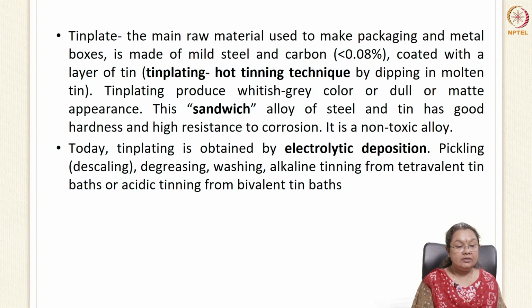Now tin plate steel is the main raw material which is used for developing cans and metal boxes. So it is made of mild steel and the carbon content is below 0.08%, and it is coated with a layer of tin, and this coating is called tinning or tin plating. This technique is the hot tinning technique, and it is generally done by dipping the sheet into molten tin, and this gives a whitish gray color or dull matte appearance to the tin. This process is like a sandwich. This sandwich alloy of steel and tin has good hardness and high resistance to corrosion, and this is a non-toxic alloy.